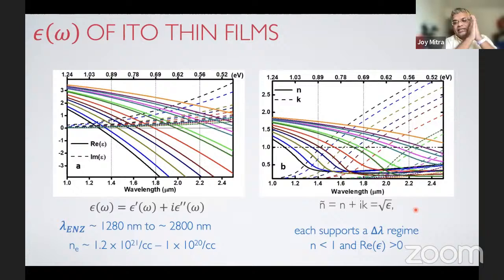Once we established the protocol, we went ahead and tried to make as many samples as we can, showing control. This is a range of selected samples from our many tries, which shows that we can tune the lambda ENZ right across from 1280 nanometers to around 2800 nanometers. This is the limit of our optical detection system that we developed in the lab in the near IR regime. And correspondingly, the number density changes by an order of magnitude, from 10 to the 21 to 10 to the power of 20.